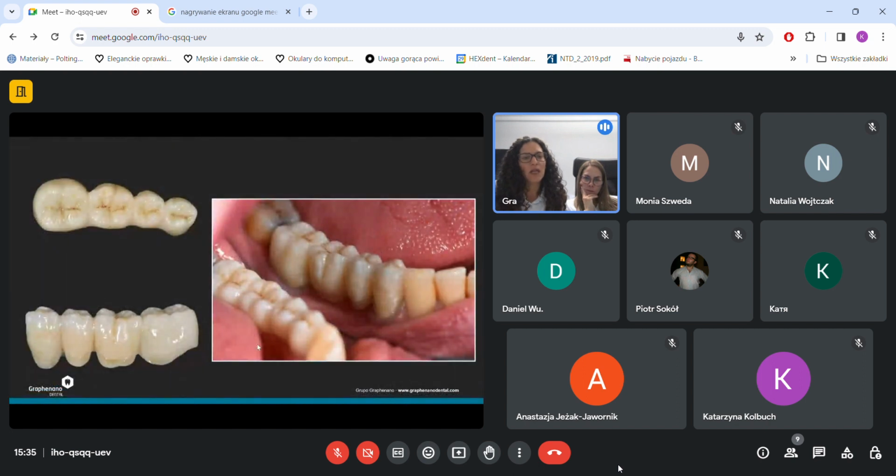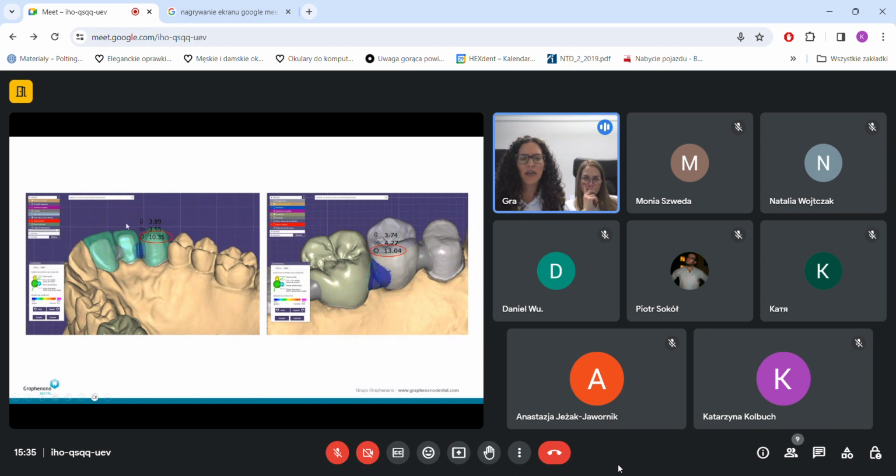Wait a second here. This will be the design. It's very easy, very similar to a zirconia bridge. Okay, I recommend, if you have two pontics in the middle, to reinforce a little bit more the palatal area, as you can see here, to make sure that everything is going to be okay. Regarding the connectors, in the anterior area they could not be less than 9 square millimeters, and in the posterior area not less than 13. Okay.